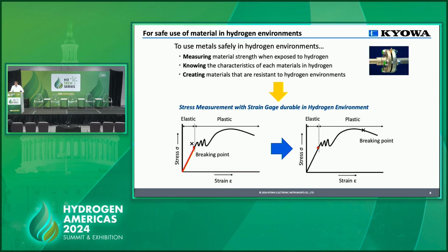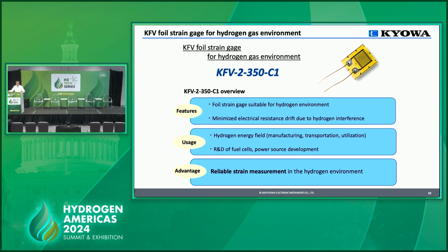In order to manage the hydrogen embrittlement problem and use metal safely in a hydrogen environment, 3 steps here are really critical for quality assurance. Step number 1, measurement of material strength when it's exposed to hydrogen. Number 2, knowing the characteristic of each material in hydrogen. Number 3 is designing and creating the materials that are durable enough for a hydrogen environment. So test engineers in the world are carrying out stress measurement by using a strain gauge durable in a hydrogen environment.